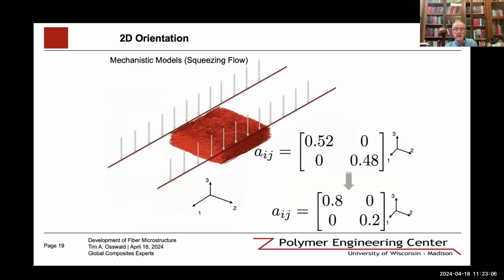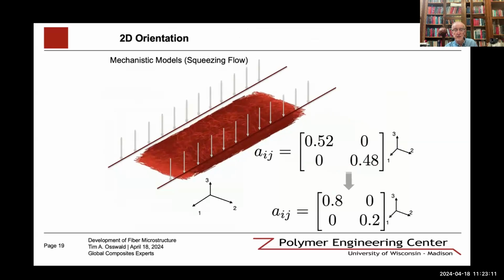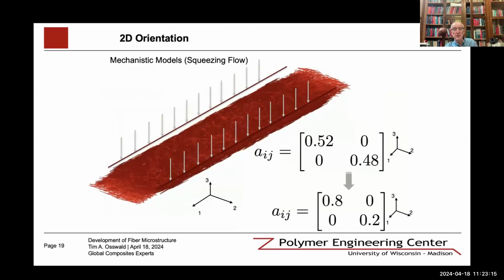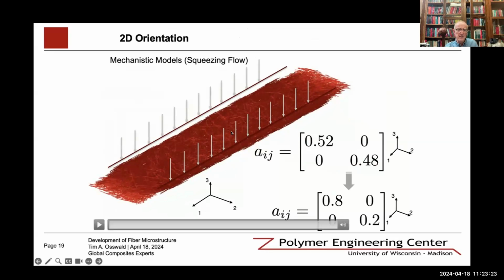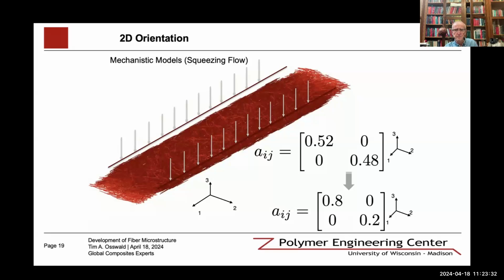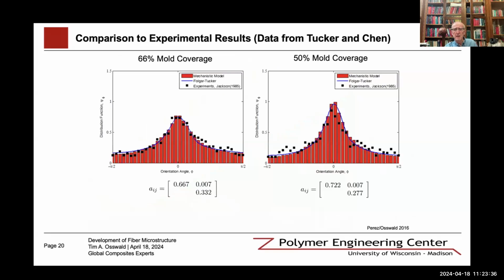If we squeeze that in one direction, as in the experiments that Chen and Tucker performed, you can see the change in orientation, in this case represented with the Folgar-Tucker models. There are other things you can see that I'll refer to a little later. You can see a change in the fiber density distribution, particularly in the flow front. If we compare the Folgar-Tucker model to the experiments by Jackson and Tucker, my mistake, not Chen and Tucker, and the mechanistic model, you can see that they all match quite well, which means the mechanistic model can represent the orientation really well, and we can use it to determine interaction parameters and fitting parameters for the various models that exist.